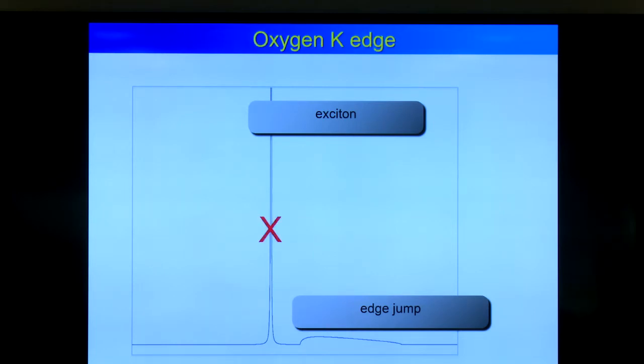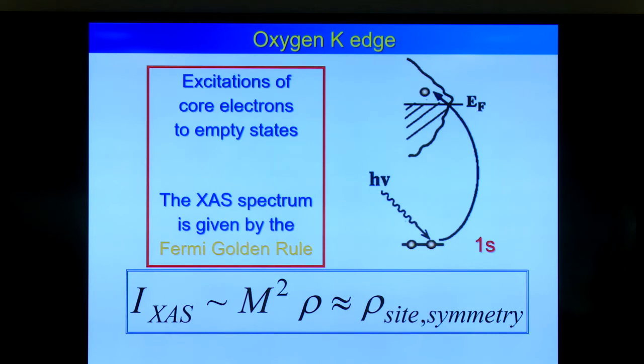So if you measure an oxygen K-edge, so the excitation of an oxygen 1s core level to an empty state, there are no excitons. So the core potential is not strong enough to create excitons, at least not in solids. And you only see band transition. So that simplifies your interpretation a lot. So you do your calculation now with your Fermi golden rule simplifies to essentially the density of states. So what you now have is that the intensity of X-ray absorption corresponds to a matrix element, which I assume to be constant for the moment, times the density of states. So you see directly in your spectrum the site and symmetry projected densities of states in your X-ray absorption spectrum.